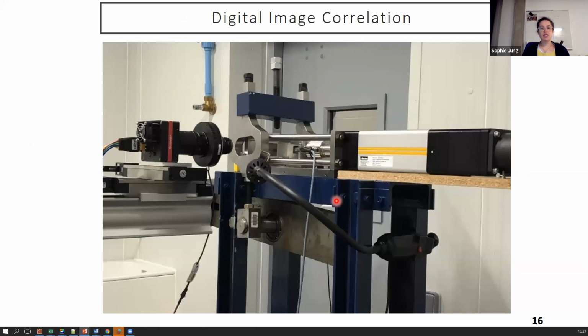Regarding the digital image correlation, we use a monochrome camera with a 150 million pixel sensor, which is quite a lot, to acquire the images. To obtain a maximum resolution of the whole sample, the camera is mounted on 2 motorized displacement stages that you can see here. 1 stage is used to move in the direction parallel to the sample here. We take each time 2 pictures of the sample, 1 of the left side and 1 of the right side